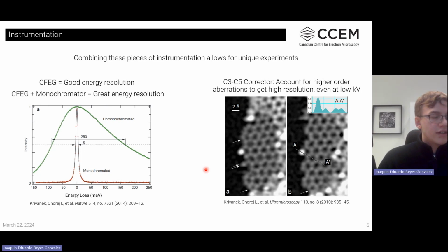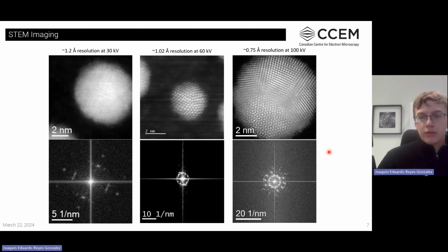To go over some of the technical details as to what we get out of our scope in terms of spatial resolution, well, it's very good. At 30 kilo electron volts, we're getting around 1.2 angstrom resolution. That's very, very nice. Typically, you're going to be limited to a lot of the thinner materials at 30 kilo electron volts if you're trying to do imaging. That's the downside. But if you're trying to do spectroscopy on, say, non-intersecting geometries, or if you want to look at 2D materials, it's amazing. 1.2 angstroms is very good at 30 kV.